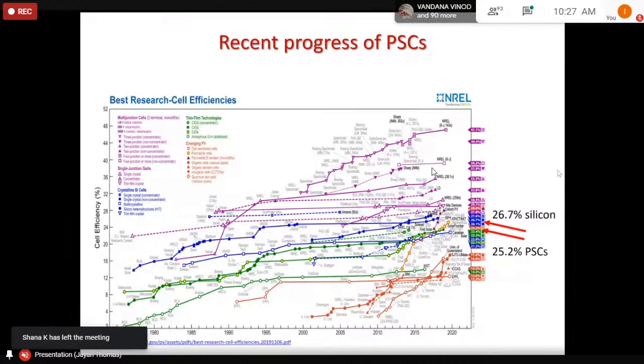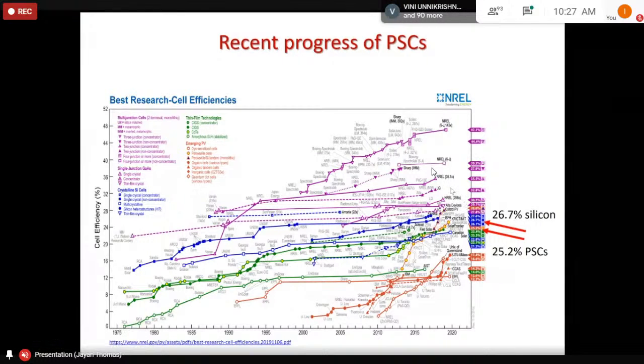So if you look at this chart, you can see some of the solar cells. This is just the performance of the solar cell. For the crystalline silicon solar cell, you can see the efficiency is about 26.7, which is shown in the blue colored plots here. It's a highly crystalline silicon solar cell. Whereas the other one, this yellow colored plot, is called the perovskite solar cell.